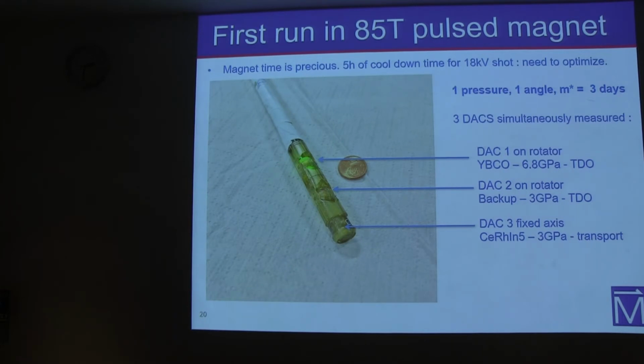And so for a pulse magnet, to get to those really high fields, you need to dump a huge amount of current in the magnet. So it means that you warm up the magnet pretty fast. It means that you need to wait for the magnet to cool down in between two pulses. So for that magnet, we have to wait 5 hours in between two pulses, which means that at best you get like 3 pulses per day, which means that you have to optimize your experiment absolutely.